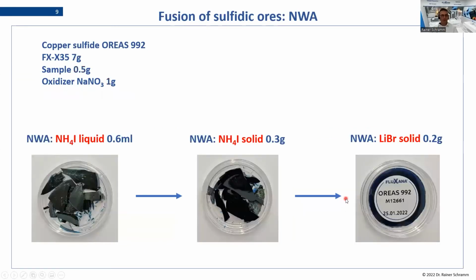Another thing we have to discuss is the non-wetting agent. Also here a sulfide example. Now it's copper sulfide. Recipe 0.5 gram sample, 7 gram, again this FX-X35 flux, and 1 gram sodium nitrate as oxidizer. And here we have 3 different non-wetting agents. Ammonium iodide liquid, let me say in a 25% solution. Then ammonium iodide solid, or lithium bromide solid. And you see here in that order, it's getting better and better, and in the end giving a glass.